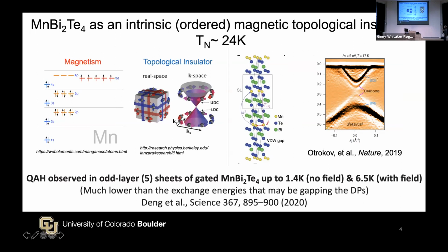From their paper, they're arguing this is the surface Dirac cone here, and it's gapped with, you can see, a quite large energy scale, many tens of millielectronvolts approaching 100 millielectronvolts. So a very large exchange field is the claim. So this really set off the field.